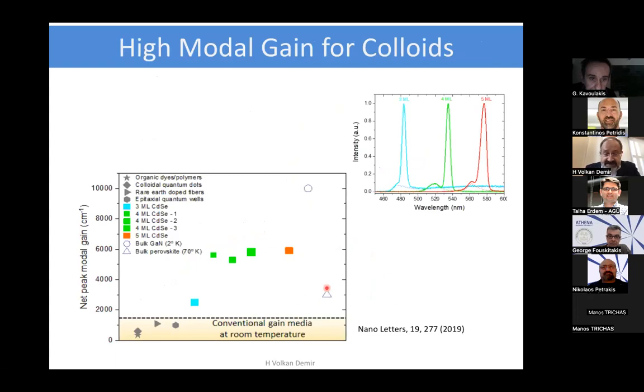If you'd like to put this in a perspective, given the best reported values in the literature, this is for organic dyes, polymers, colloidal quantum dots, rare earth doped fibers, epitaxial quantum wells. These are all at room temperature and the best in their classes. We see that at room temperature, they can only achieve certain level of peak modal gain, as opposed to this very promising group of materials. These are all cadmium-based, cadmium selenide, colloidal quantum wells of 3 monolayers, 4 monolayers, and 5 monolayers, all again room temperature, providing higher gain.